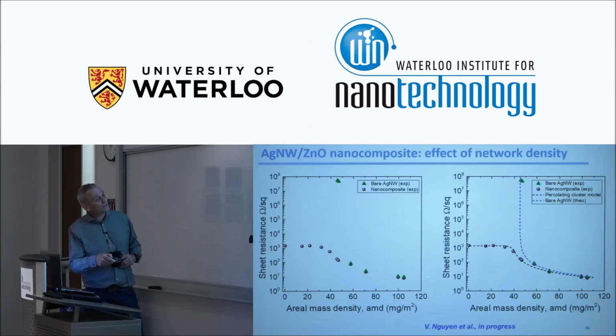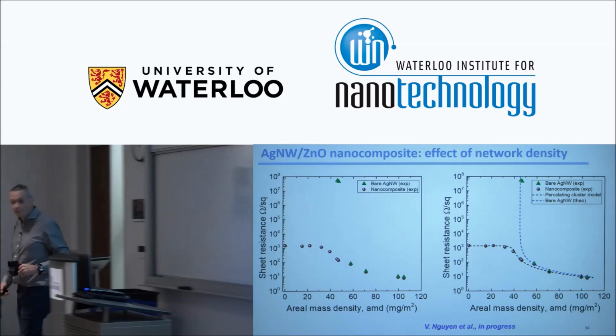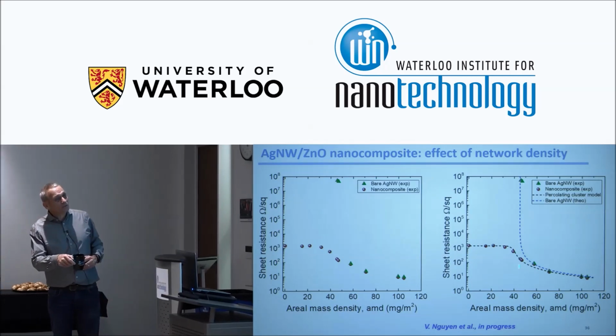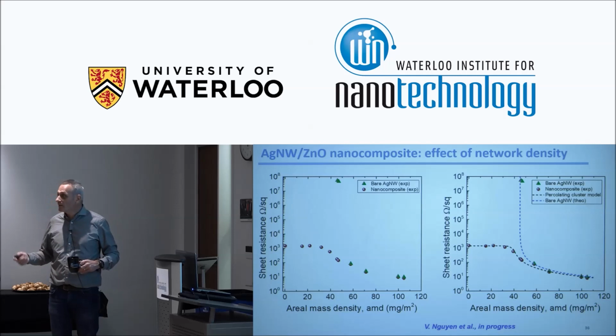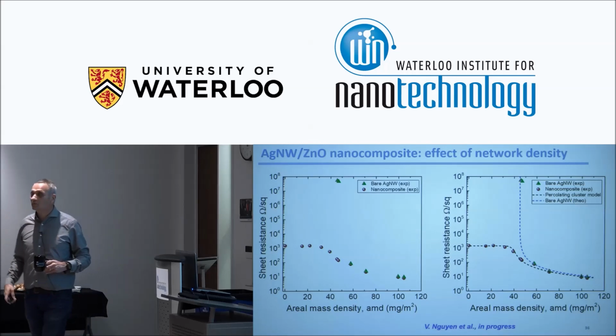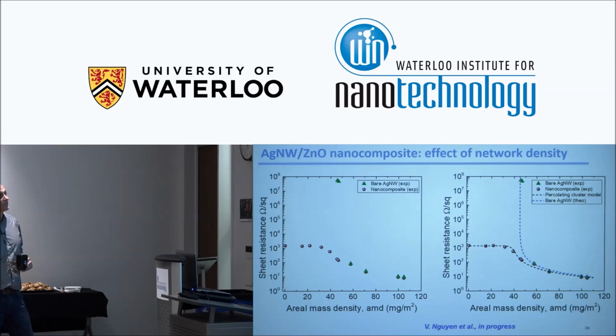We can clearly see there, as before, that there is a critical areal density somewhere here. And here, this is a nanocomposite when we put the zinc oxide layer and the silver nanowires. And we can fit that easily with some simple models. This is only the percolation theory I was talking about before. And this one is a kind of new model, which we call the percolation cluster model. So it's interesting to see that even below the critical areal density, it's possible to help the conductivity of the zinc oxide layer by integrating some silver nanowires, even below the critical threshold. That's something which is rather interesting as well.